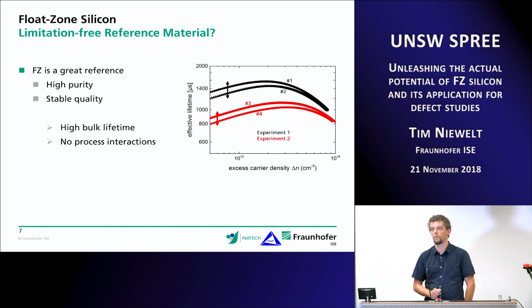this is the next experiment that I did, and we see a very different lifetime level that we wouldn't expect from a float zone wafer. And again, we see this small variation of the process, but the overall lifetime level has dropped significantly. And our technology guys promised me that it wasn't their fault, so they did the same thing as before, which leads to the thought maybe float zone is often not a great reference material.